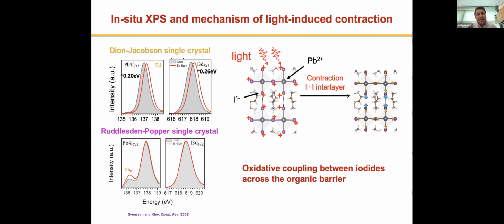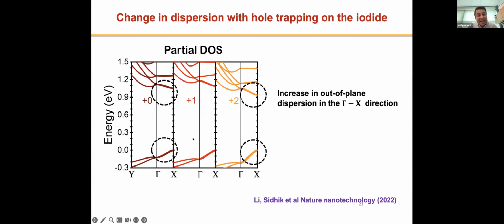Okay. Now, if you're a theorist, you can think of this as putting positive charges, like polarons, on the iodide sites. If you do that, and calculate the band structure in the out-of-plane direction, which is from this gamma to the X direction, what you find is an increase in the slope, or more dispersion in the out-of-plane direction. If you remember, in the beginning I showed you that typically this dispersion is pretty flat in this direction. But now with light soaking, as you bring these layers closer, you start to get a much higher dispersion. This means that you may have opened up a transport channel in this direction, or a higher propensity for charge transport across these layers.